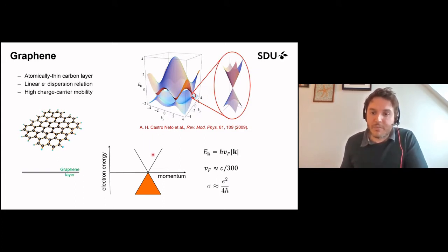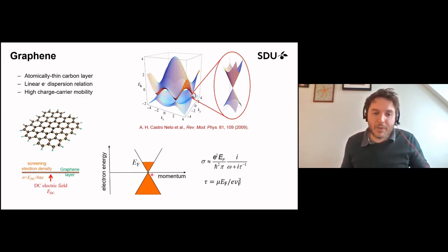And from a technological standpoint, what's really fascinating about graphene is that if you just have graphene isolated in vacuum, it has this simple band structure where electrons are sitting in this low energy cone. So it's like a zero gap semiconductor. But if you can apply an electric field to the graphene, you can effectively increase the charge density in the graphene layer, so adding some electrons. We call this doping the graphene. Then you can increase its Fermi energy, the highest occupied state in the electronic structure, and it essentially becomes a metal. So it has electrons that can move around in this dispersion relation, and you can describe it by this simple optical conductivity that characterizes the optical response.